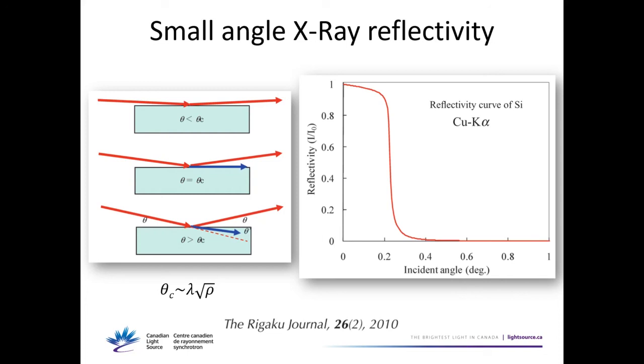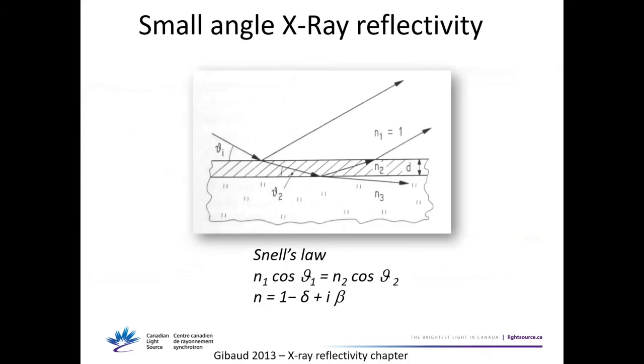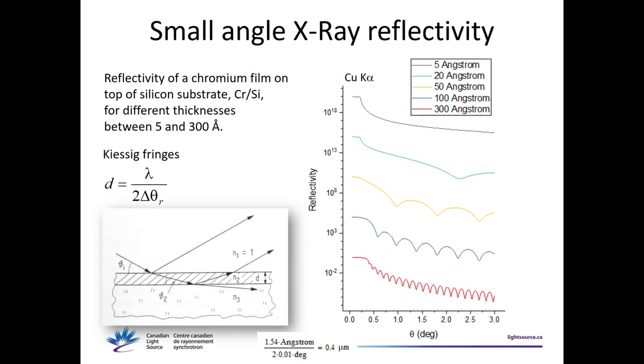The critical angle gives information about the material. With interfaces, a beam will reflect at each interface and go up, and if there are more films, it will reflect at every interface. The beams coming out will interfere, either constructively or destructively. This interference gives rise to typical oscillations you can see in the reflectivity of thin films, and these oscillations can be used to extract the thickness of the thin film using the formula for period delta-theta and thickness d.